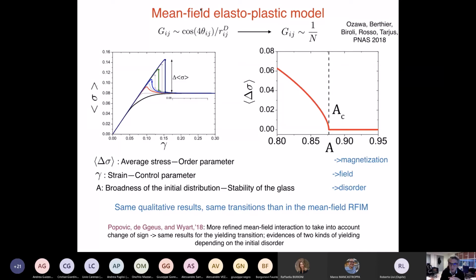And then the other interesting news is that you can also simulate the model in 2 dimensions, and you can try to see whether in the simulation you can find a phase in which, at low disorder, there is an abrupt change in the sigma versus gamma curve, and instead, when the disorder is strong, the behavior is smooth. And the answer is yes, is what they found in this paper by Matthieu Wyart. So this means that, at least from this study, this analogy with the random field Ising model seems to be good.